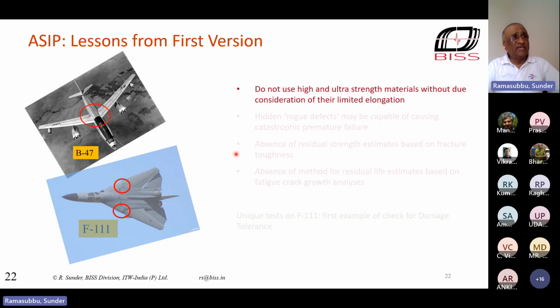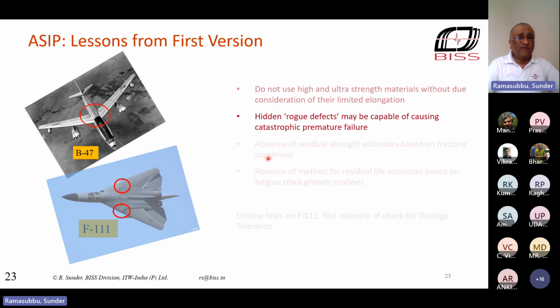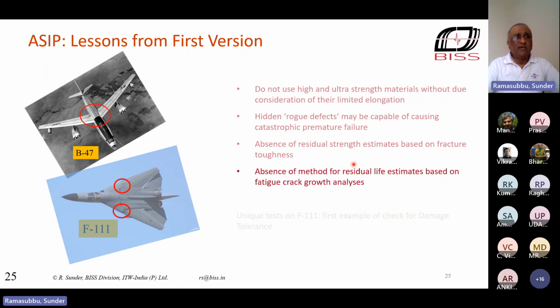The problem with the F-111 was that it had what you can call rogue defects. That 100-hour fracture, or catastrophic failure of the wing, was because there was a rogue defect in the weld, which caused early crack growth. And that was compounded by the absence of residual strength estimates. Because fracture toughness, though it was a parameter already well known in the science field, the importance of that was not appreciated enough in the construction of this aircraft. And there was no method available at that time for residual life analysis based on fatigue crack growth. So that was the situation with this aircraft.